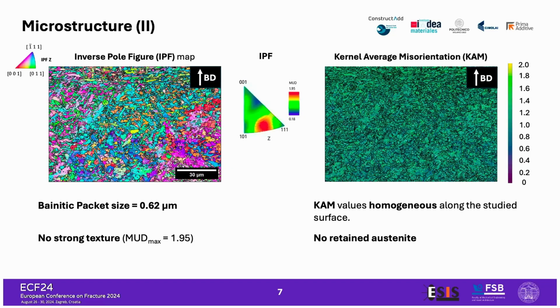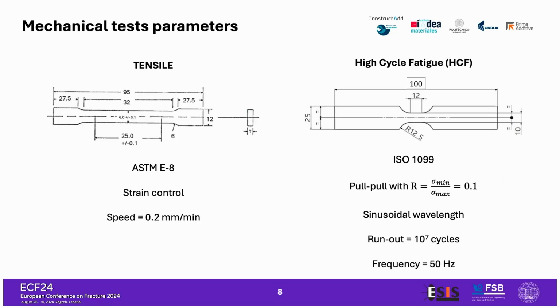From the EBSD analysis, we assessed just a slight texture between the 101 and 111 directions. We assessed the bainitic packet size at less than 1 micrometer of equivalent diameter as an average value. And we also assessed the kernel average misorientation distribution, and we saw that actually we have a uniform distribution of the KAM values with no retained austenite from the process. So now let's move to the mechanical tests.